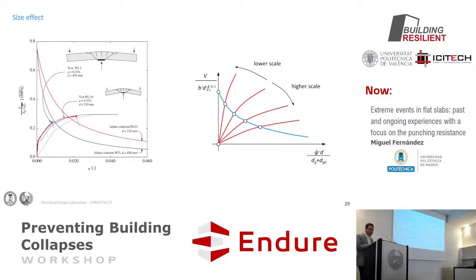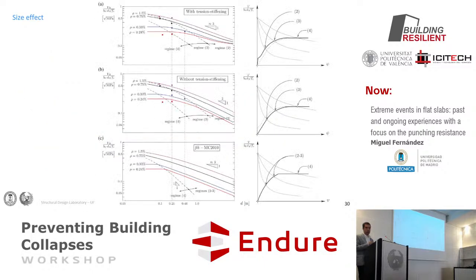And this, without plugging in any coefficient, without doing any trick, you can express in terms of a double log scale, and then you get what is normally called not only the size effect factor, but the full size effect law, as described, for instance, by Bažant. Depending upon your considerations, it may vary a bit. For instance, for the parabola, you have this decay. It is going up to a limit, which is the strength criterion. This point here cannot be higher than this point. But when you have larger sizes, it decreases about a slope of 1 to 3.